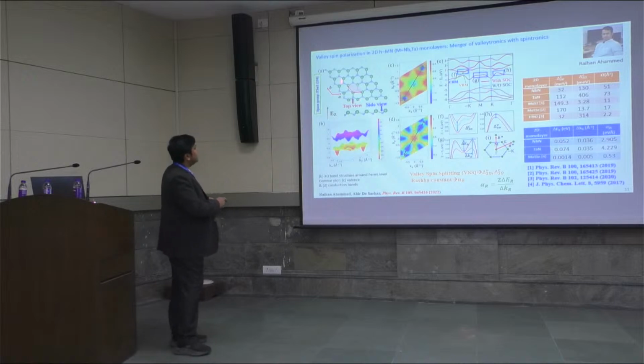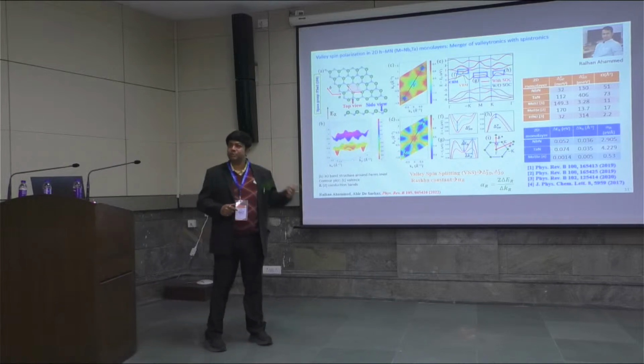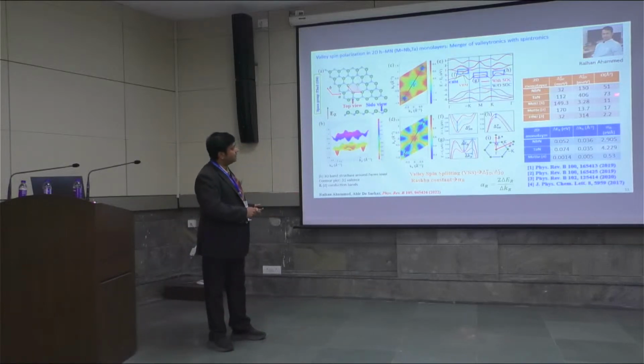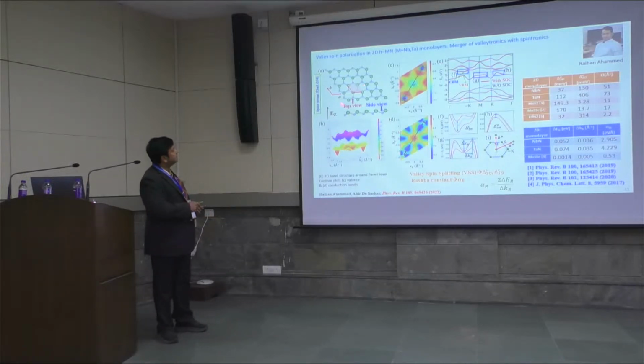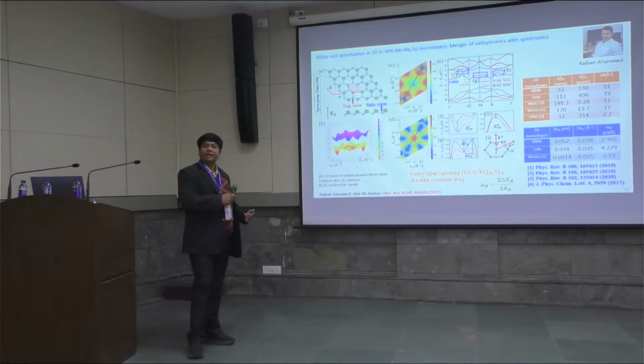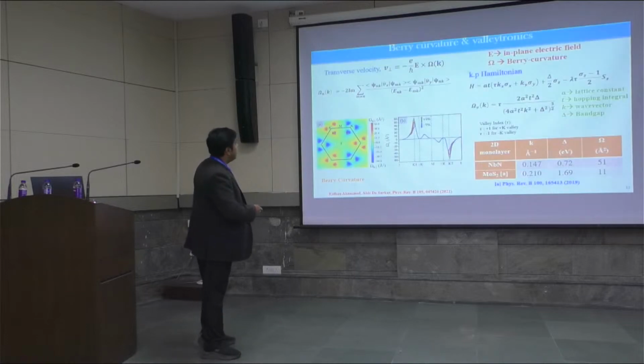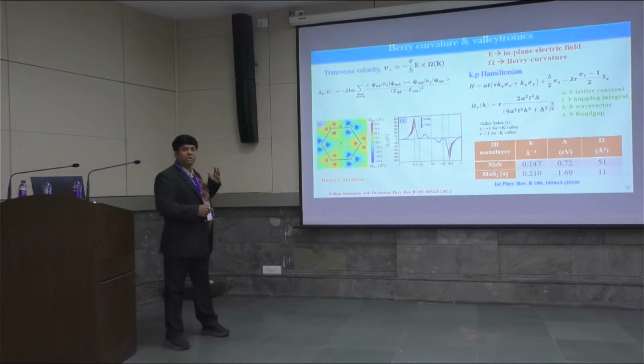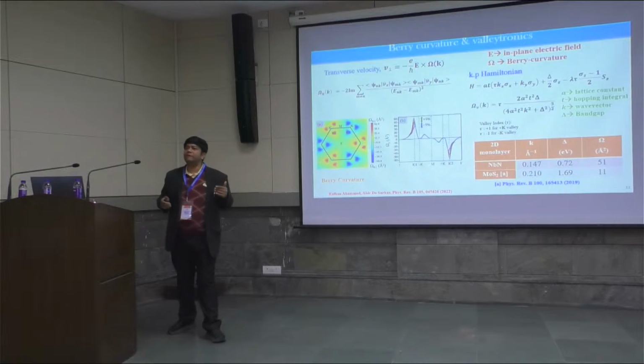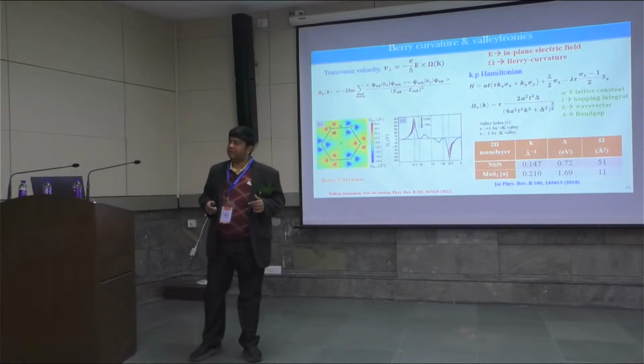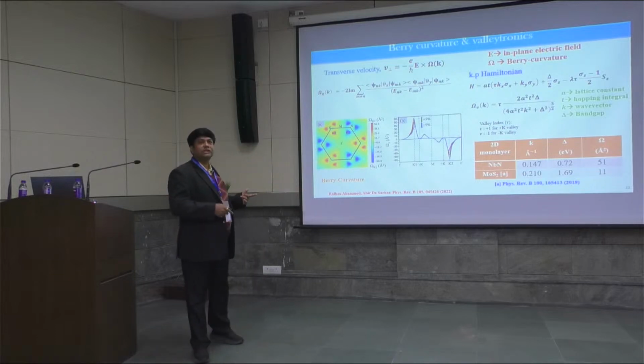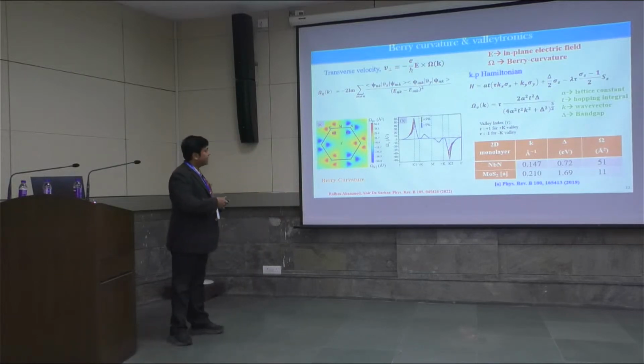And also it has a large spin orbit coupling, and the inversion symmetry is broken, and therefore it shows a high Berry curvature which is much higher than several two-dimensional materials. So this also shows a reasonably good Rashba constant, and therefore we propose that these monolayers will be suitable for the integration of valleytronics with spintronics. And also what we find here is that these 2D materials are stretchable and flexible. They have a low elastic stiffness constant, and therefore it is worthwhile studying the response in the material properties to the application of mechanical strain. That is what we have done over here.